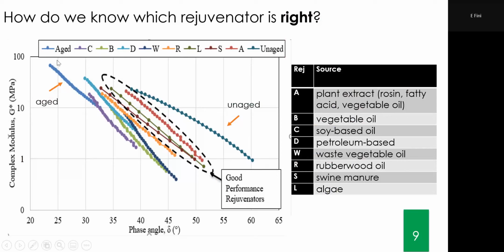You can see here the aged material is the blue. When we added all of these rejuvenators, they changed the complex modulus in different ways. Here I put the unaged for you, so you can see the unaged and the aged. If I had the perfect magic that I could just convert aged to unaged, then I would get a curve like this. The unaged one. But as you can see, all those curves have different slopes and different distances or closeness to the unaged. One thing that is very noticeable is a group of them, in this dashed line, having almost the same slope, and another set did not even change the slope.